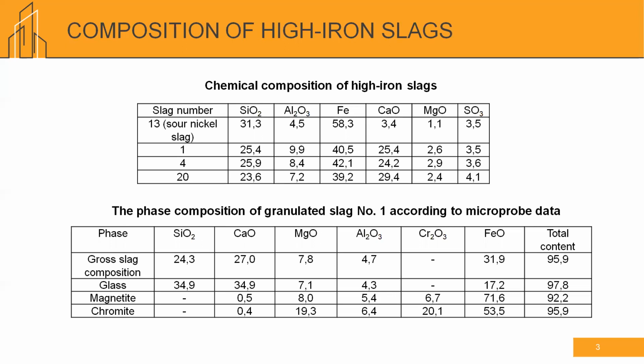For the experiment, we used slag Portland cement on a special nickel slag of increased basicity, with chemical and phase compositions according to the tables presented. Slag Portland cement was obtained in laboratory and industrial ball mills based on clinkers from the Achinsk and Norilsk plants with a slag content of 30%.